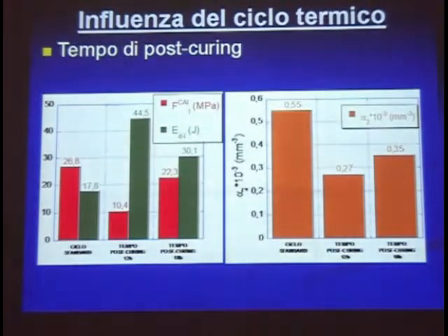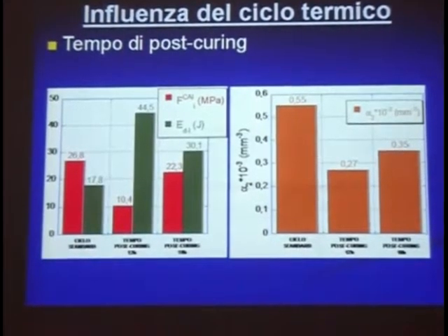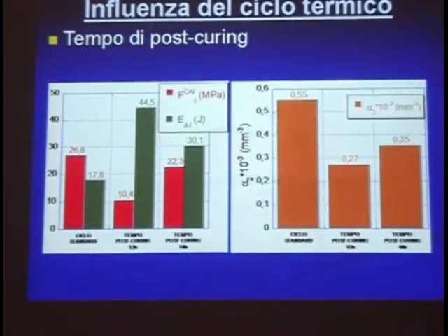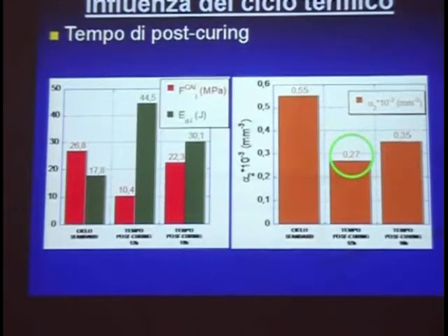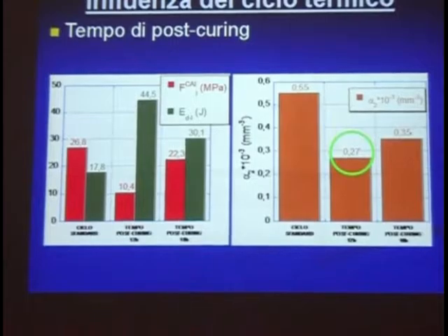And also the critical energy is also somewhat up and down, so you can't get a clear picture from this plot. But at least with the slope, there seems to be some decreasing trend going from the standard cycle to the post-curing at 12 hours and then the post-curing at 18 hours. The lower is the value of the slope, the higher is the ability of the material to withstand further damage for increasing impact at high energy. This is the more interesting, probably, condition, 12 hours post-curing time.